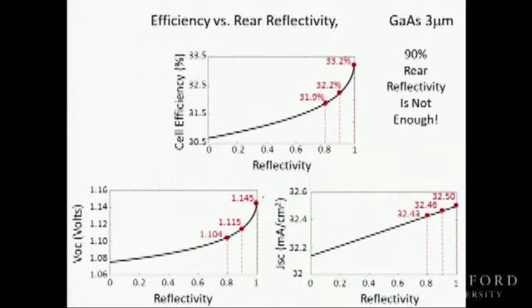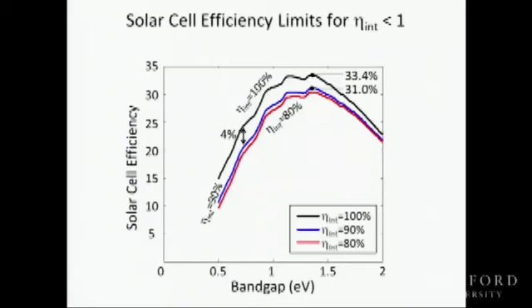And you usually have to have a reflector to avoid losing the photons. Again, a reflectivity well above 95%, because most of the benefit occurs up here, above 95%. So that's quite a severe challenge. Now, how to think about this?